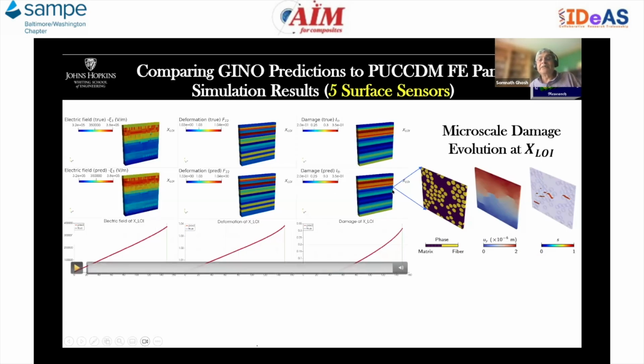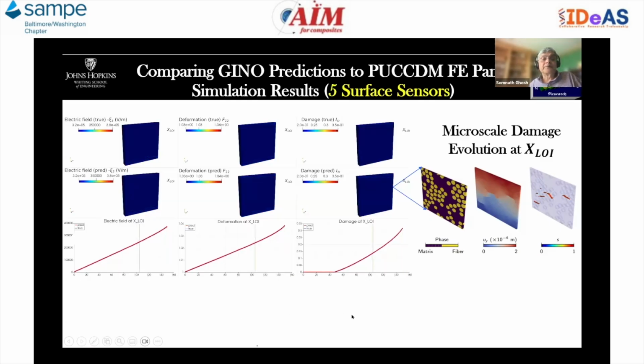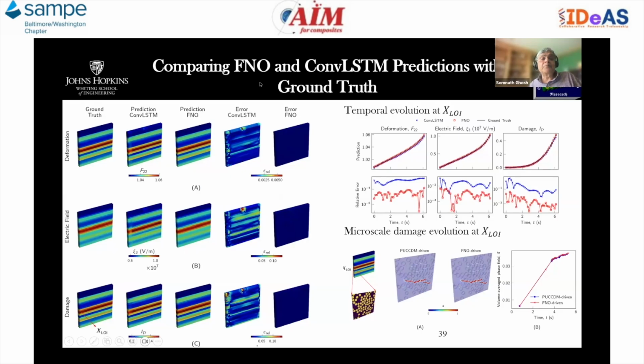And then we identify a location of interest at which we can recreate the microstructure. This corresponds to the mechanical field, the displacement field, and this corresponds to the damage evolution in the microstructure. This is a comparison of the FNO and ConvLSTM. As you can see, these are predictions. This is the ground truth, prediction by the ConvLSTM and predictions by the FNO.